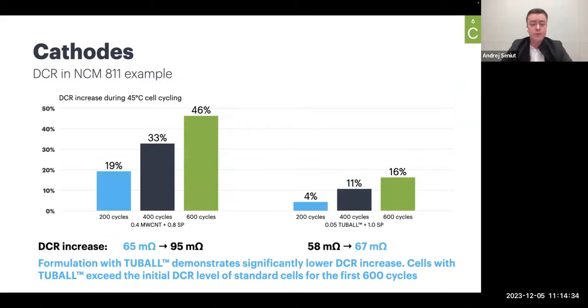Lower DCR, so to the left, this is the control group with multiple carbon nanotubes 0.4 plus 0.8 carbon black. And first of all, in comparison with groups which are to the right, 0.05 TUBALL plus 1% of Super P. So what you can see, first of all, initial DCR was lower, 65 milliohms versus 58 milliohm in groups with TUBALL. And also the DCR growth was slower with single carbon nanotubes in the recipe of the battery. DCR grew in multiple carbon nanotube group to 95 milliohm, whereas with single carbon nanotubes to 67 milliohm.